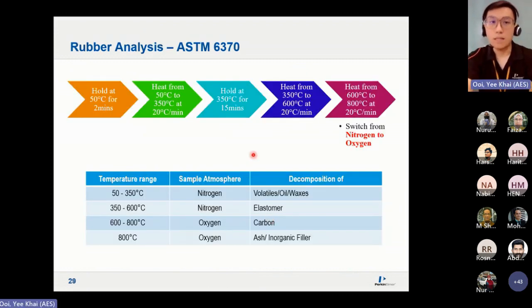So this is a standard method for running rubber materials. As we mentioned just now, usually less than 300 or 200 is your volatiles, your oils, then your elastomers or polymer. Elastomer is also a type of polymer, like I mentioned. Usually by 600, 650, most of it is gone. So in order to analyze carbon, you need oxygen. So what else is left over? This is your fillers or ash.